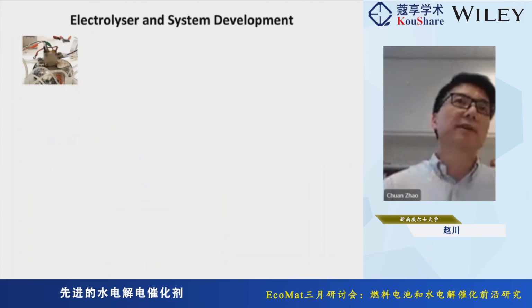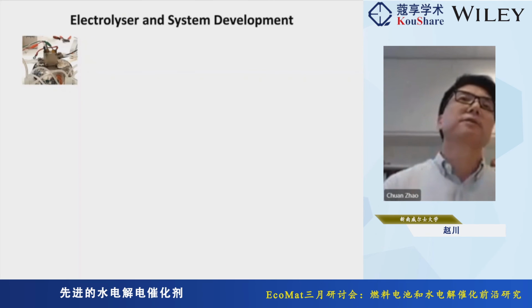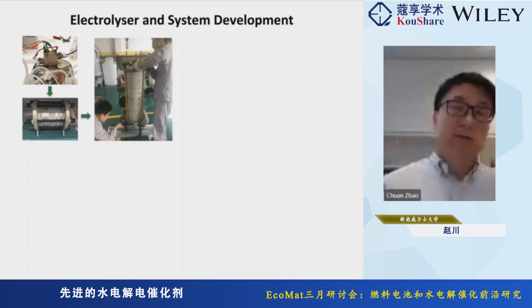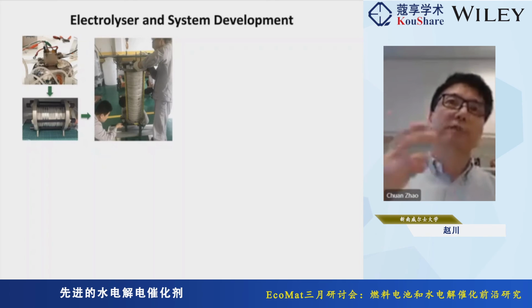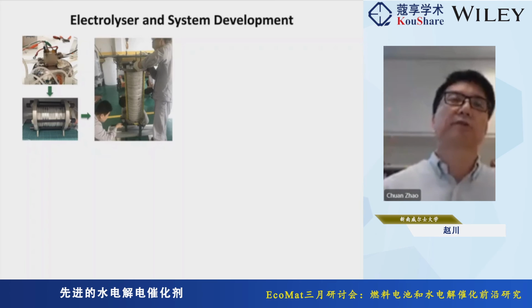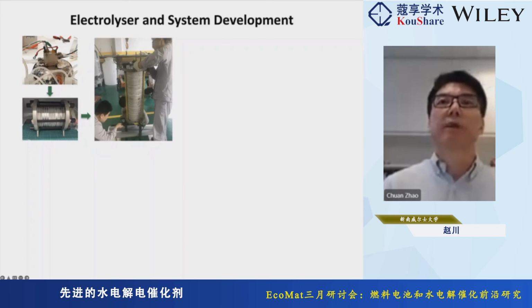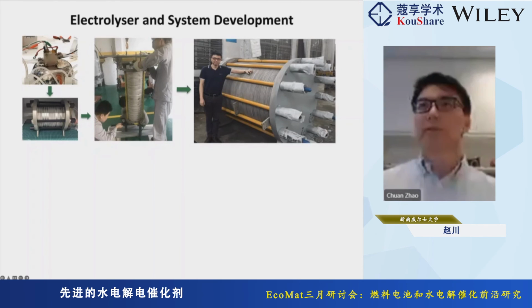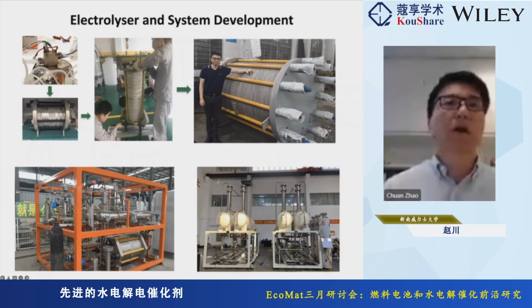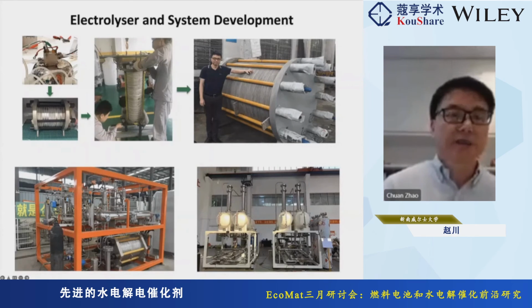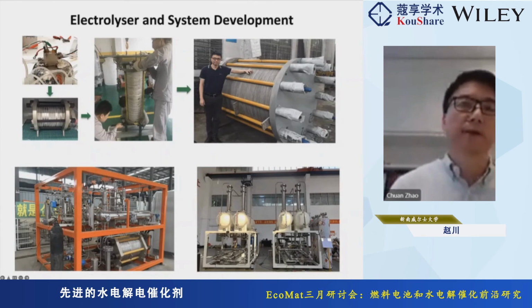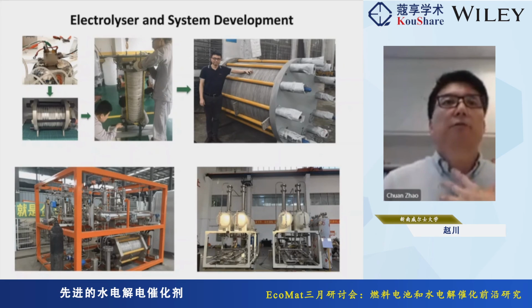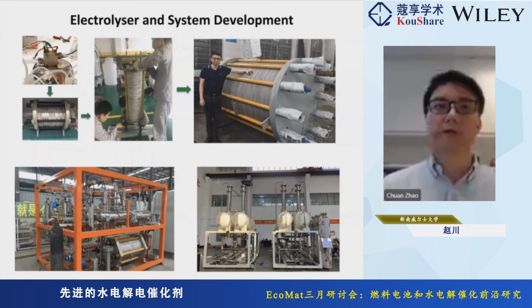So a good catalyst does not necessarily mean you have a good electrolyzer. When you scale up the catalyst and put them in the electrolyzer, the story is often different. So we've been trying to design our own electrolyzer from this lab scale stack to the bigger one, and also try to apply for these monster electrolyzers. Besides the electrolyzer itself, there's actually a range of systems built around the electrolyzer, like electrolyte circulation or gas separation. There's lots of room to improve in order to get a higher hydrogen production and reduce the cost.